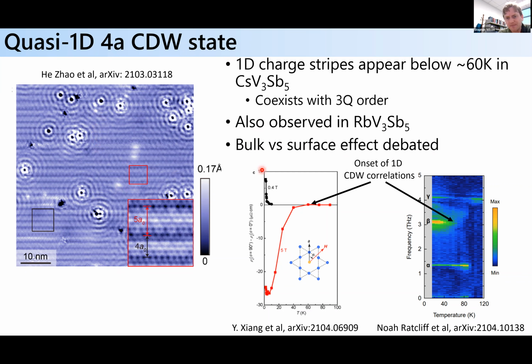going on in the bulk, meaning if you look, this is again these sort of transient optical reflectivity measurements from John Harter's group. These are the phonon modes, this phonon mode in particular analyzing below the CDW, but you can see there's sort of this broad spectral weight, a component of the oscillations that turns on below the same temperature of 60 Kelvin in the cesium vanadium-3 antimony 5 system. Okay, so there's certainly some sort of bulk response that's turning on in the lattice spectrum of these systems below the same temperature scale in which you see these one-dimensional charge modulations turn on. So I think this is supportive of a bulk effect.